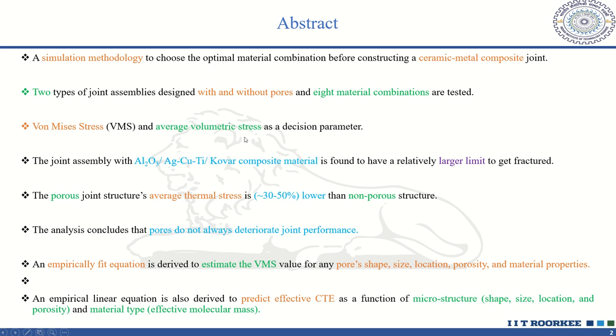Von Mises stress and average volumetric stress parameters are used as a decision parameter. The analysis concludes that the joint assembly containing alumina ceramic brazed to Kovar material using Ag-Cu-Ti brazed alloy is found to have a relatively larger limit to get fractured. It is found that the porous joint structure's average thermal stress is 30 to 50% lower than the non-porous joint structure. The analysis also concludes that pores do not always deteriorate joint performance.